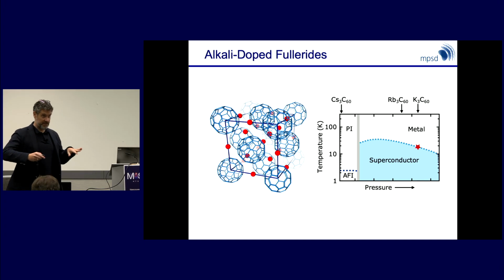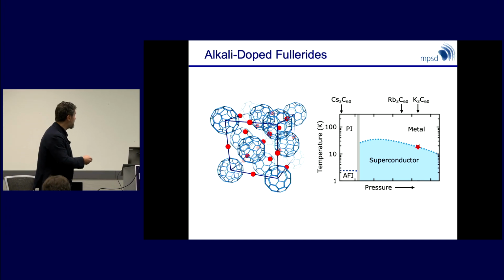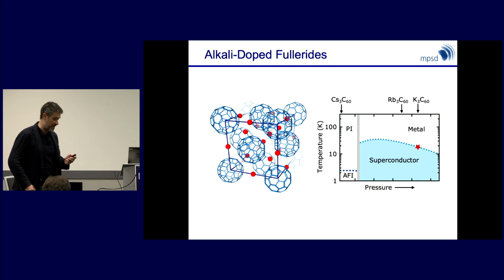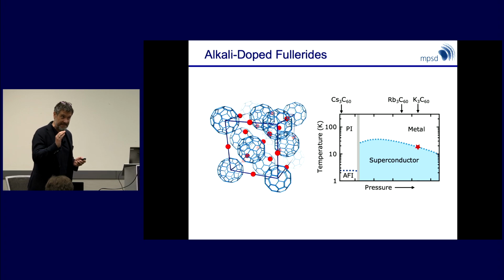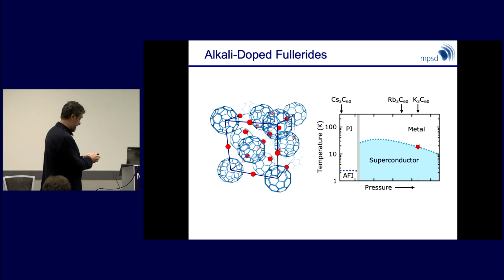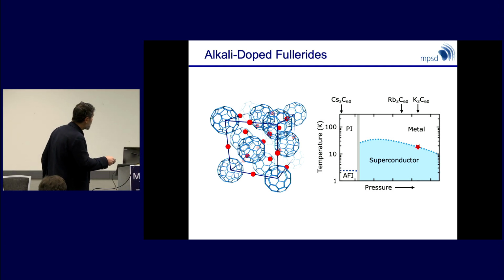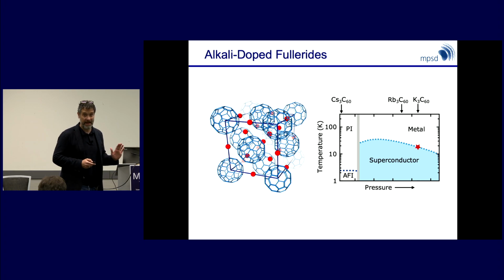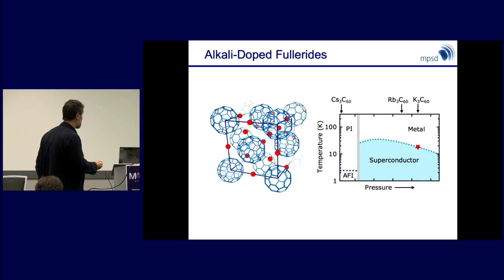So let me just focus on the problem of the Fullerides. This has been discussed in some detail during this workshop. Think about an FCC lattice of 3 times doped C60 molecules. In the case of potassium doping, this is a 19 Kelvin superconductor. If you take cesium and put it under pressure, you can reach a transition temperature of even 40 Kelvin. For a while, these were the highest temperature organic superconductors.